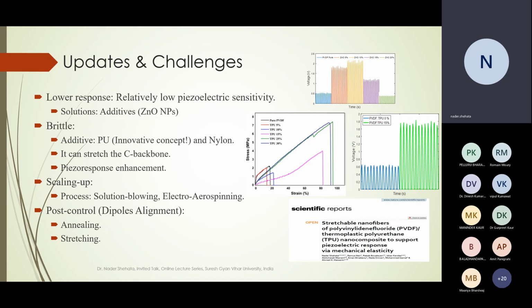But there are other techniques related to post-treatment or post-control, where you already have ready-made PVDF nanofibers, okay? But you can control the dipoles and increase them using different strategies, such as annealing. Some literature talks about annealing up to 100 or 120 degrees. It could enhance the orientation of the piezoelectric phase once it becomes dried. Also, the stretching itself: if you can stretch the PVDF, then you are stretching the carbon backbone chains, and consequently you can increase the dipole moments, as I said, between the fluorine and the hydrogen, or from the positive and negative dipoles, and consequently you may have a higher piezoelectric response.